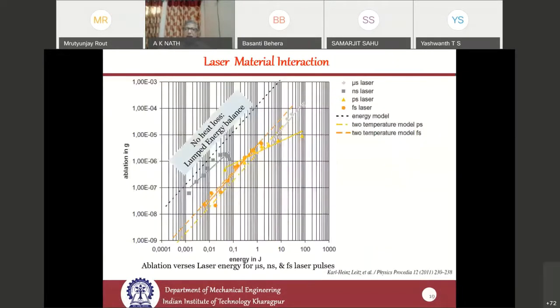And based on all these effects, one has tried to find out, for a given laser energy, how the ablation per gram depends on it. This line shows the lumped energy balance equations based on the previous equations I mentioned, for nanosecond and microsecond laser pulses, where the losses are very minimal. And here it is for femtosecond laser, where the phenomena are very, very different.